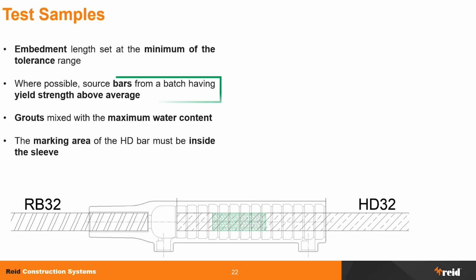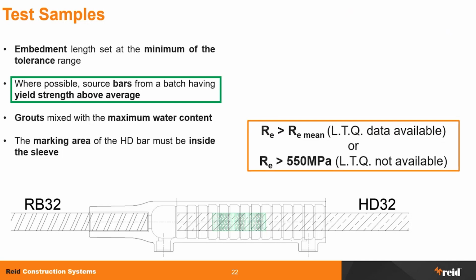Then we look at the batches of the bars that we sourced. When we sourced the bars for testing, the idea was to try to get stronger bars than average. This is something that we've been inspired by the ISO 15698, which does a similar thing. So if the long-term quality data for the bar was available, we checked that the ReH, which is the yield strength, was above the mean for the long-term quality. Or if it's not available, above 550 megapascal, which is in the middle of the range of the 500D grade bar, which is between 500 and 600.